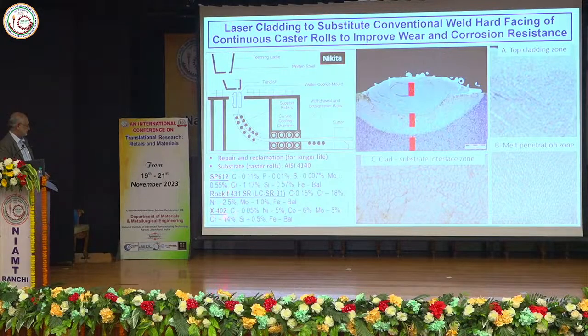This is high nickel, so this is austenitic, and this is also a semi-martensitic variety. So she wants to try with different compositions. The base substrate is 4140, low alloy steel. If you start with a low alloy steel instead of a high alloy steel, and change all these casters to low alloy steel and then clad it with one of these clads, while still retaining or even offering better corrosion resistance and better high temperature resistance, then the company stands to gain a lot.